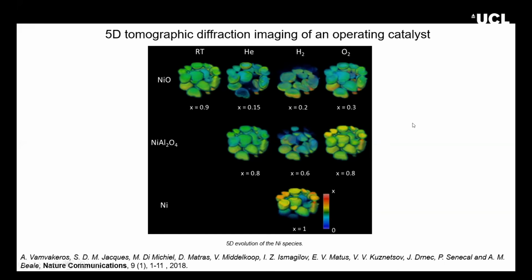So as I mentioned, most of the time we're getting data from a 2D cross-section, and yet the samples show variability in height. So we have this challenge that it's not good enough to just measure a cross-section. We really need to get a volume. So that's what we've been doing in the last few years, taking advantage of the fact that the X-rays are bright and the detectors are sensitive, to actually do a Z profile. So essentially doing lots of 2D cross-sections at different heights. And that's the result that I'm showing you here.